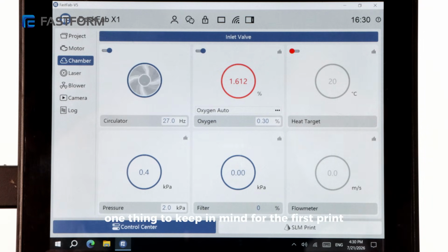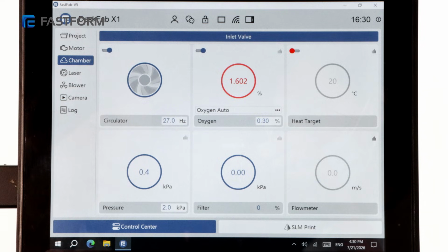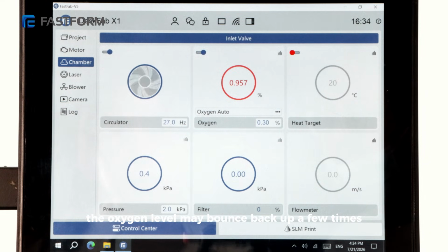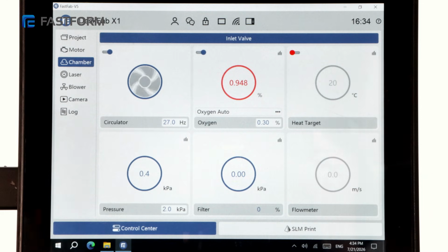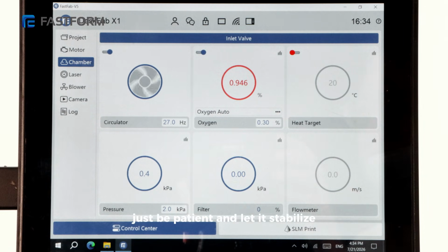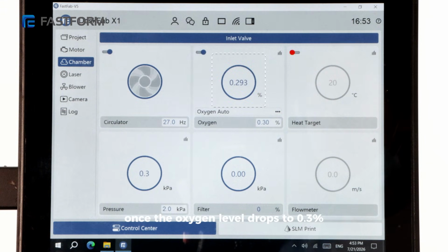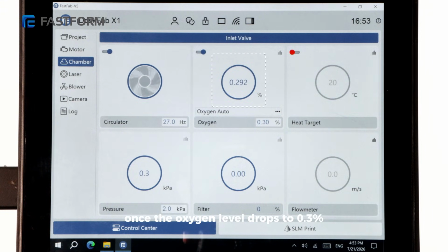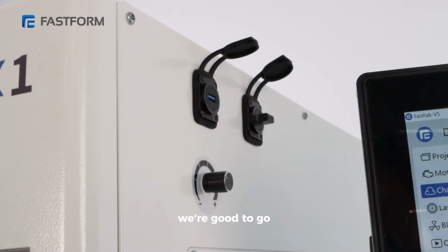One thing to keep in mind, for the first print, the oxygen level may bounce back up a few times. That's normal. Just be patient and let it stabilize. Once the oxygen level drops to 0.3%, we're good to go.